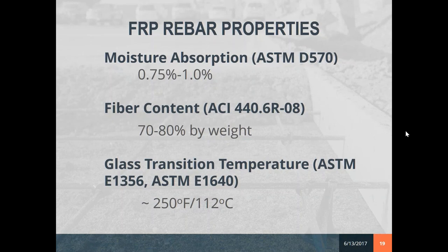Everybody wants to know if they melt, if they burn. In our particular case, we hand out these small, about 3-inch samples. Everybody always tells me they look like cigars. They want to know if you can smoke them or if they look like beef jerky. I don't recommend either one of those, but they generally will soften around 250 degrees. That's the glass transition temperature. You'll see that in a lot of the specifications.